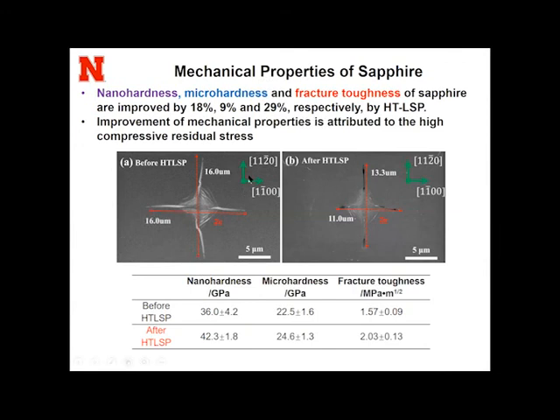After the high temperature laser shock peening, when we study their mechanical properties by both Vickers indentation and nanoindentation, we found the crack length is significantly reduced, which indicates fracture toughness increase. And the table here shows the measurement of the nanohardness, microhardness, and fracture toughness. You can see all of them have a significant increase. And again, the mechanism for this is because the high compressive residual stress reduces the stress intensity factor at the crack tip.